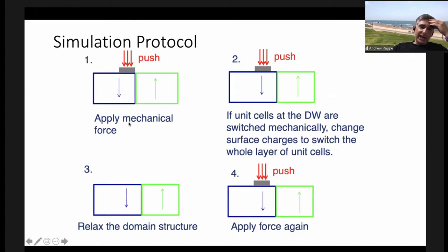Okay, so what is our protocol? We push with some mechanical force. And if some unit cells at the domain wall switch, then we change their surface charges, because once it goes from up to down, the passivating surface charge would have to be different. And then we relax the domain structure, and then we push again. And so that is the simulation protocol.